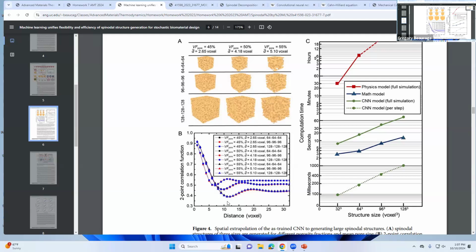And you see a depletion, nearest neighbor depletion, then you have a peak because this is a periodic structure. So in other words, it doesn't look periodic, but the distances between the phases are always about the same size, so you get a peak in this. That's a signature of spinodal, right? And then you go out, that oscillation for yes, no, as you go out, eventually dampens out because it averages out to the average density of the thing. So here's the average density.